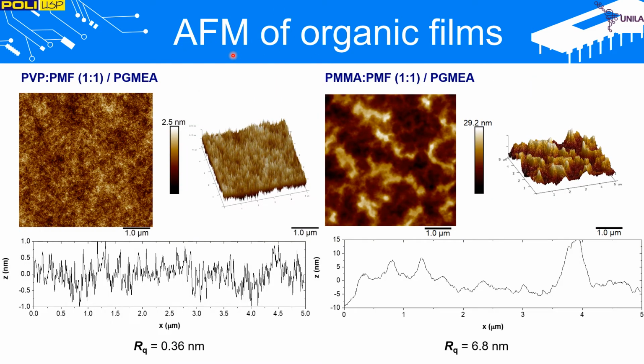These results of atomic force microscopy demonstrate that the surface roughness of PVP with PMF films is not severely altered by the cross-linking process, since the results found in the literature for PVP films without cross-linking change only slightly. In addition, these root mean square roughness values are adequate for application in OTFTs, while PMMA with PMF at the same ratio featured a root mean square roughness of 6.8 nanometers. A rougher film could be originating from a lower spinning frequency. Higher rotating speeds are necessary for OTFTs, since semiconducting film thickness can be even lower than 20 nanometers.